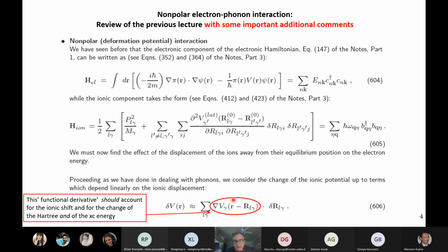And as we will see, for example, today with density functional theory, what we do is we calculate the total energy of the system. Then we calculate either by using perturbation theory within density functional theory, or by using approximate methods like displacing each ion away from its equilibrium position along the 3 Cartesian coordinates by a small amount, and calculate the total energy.